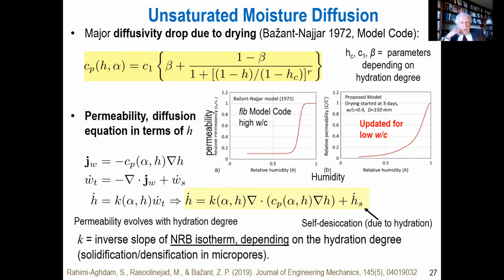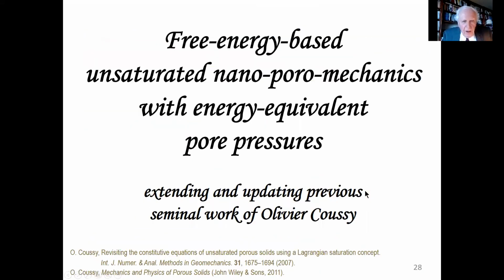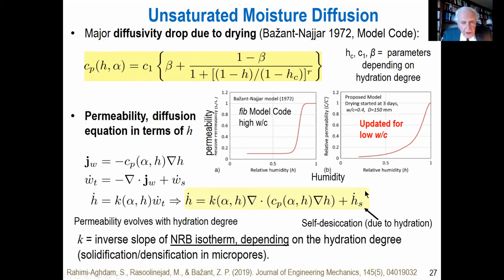Why? Because hydration changes humidity very little, especially in the original concretes with high humidity. On the other hand, it consumes lots of water and changes water content enormously. So you have a more complicated equation in terms of water content, and bigger errors than in terms of humidity. This is somewhat unusual, because in all the other applications there is concentration of the mass diffusing, or pressure as such, but this is relative pressure for humidity.